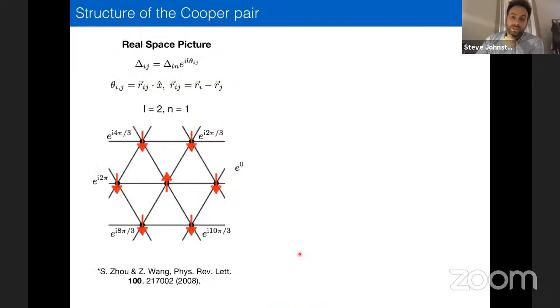So the first thing we did, just to give you a real space picture of what this looks like: the idea in these chiral superconductors is that you have nearest neighbor pairing, or you can have longer range pairing, but here I'm showing it for nearest neighbor pairing. Cooper pairs are formed from one spin on a central site and then the neighboring spin distributed on the neighboring sites, with a phase factor given by this angle, which winds by 60 degrees as you rotate around.